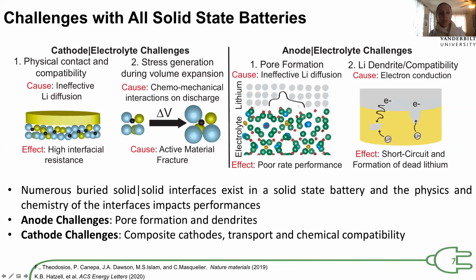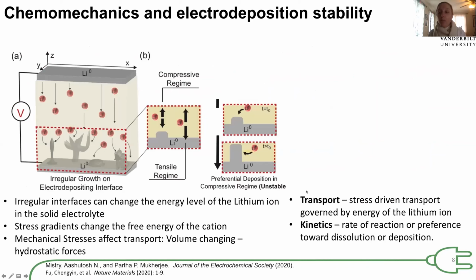And I just wanted to point out some work from Purdue that has been instrumental in inspiring some of our work, where Partha's group had a very nice paper which highlighted the opportunities for stable electrodeposition, showing that if you have preferential deposition from a region which is under tensile or compressive stress, you can form these dendrites. But if we can change where the lithium prefers to deposit, we can get a stable deposition.